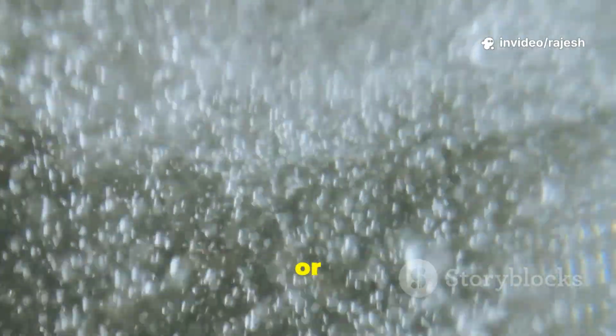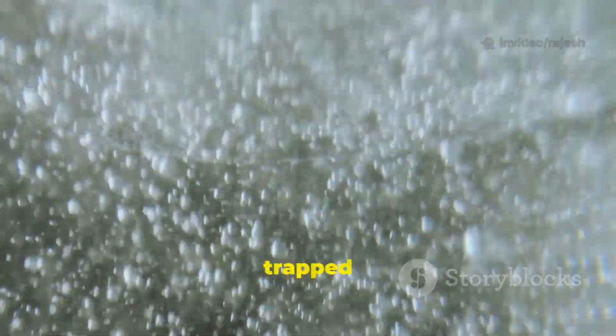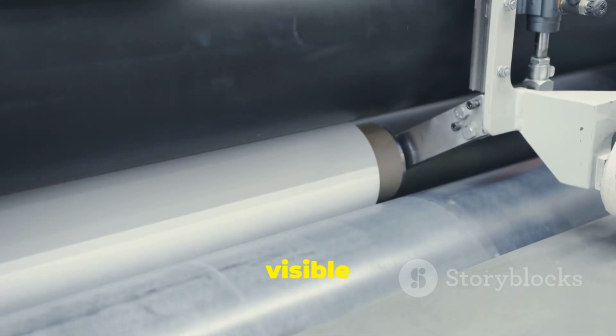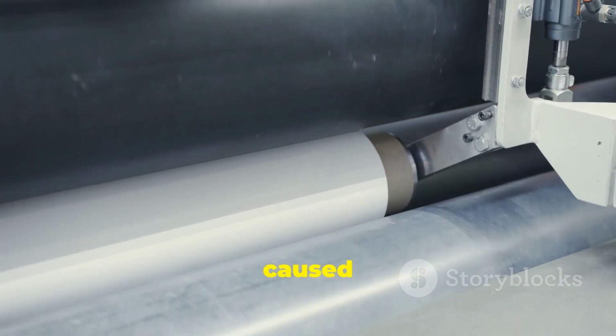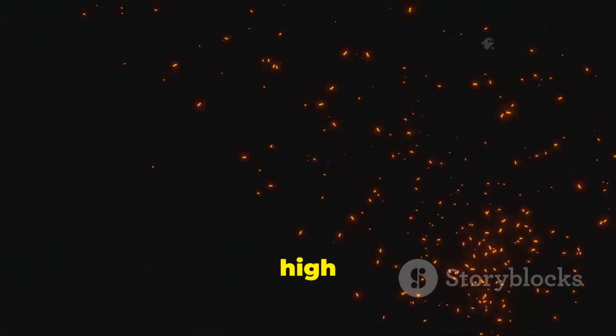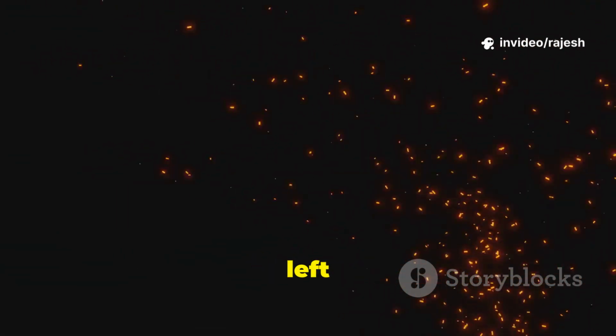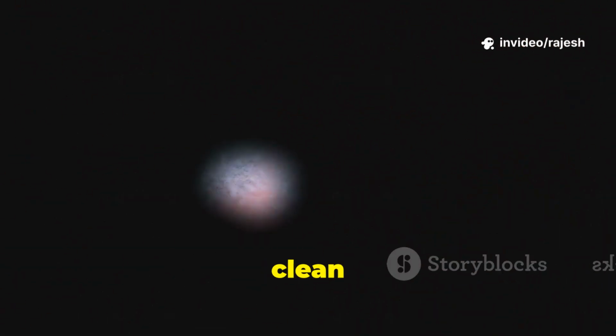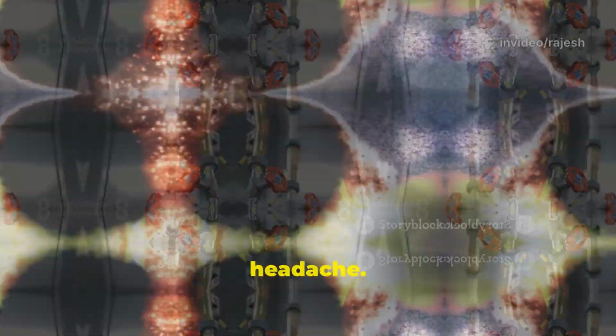Number 6, voids, or bubbles. You'll spot these as trapped air inside the plastic, often visible in cross-section. This is caused by air not escaping the mold, high injection speed, or even moisture left in the pellets. Keep your vents clean and your material dry to avoid this headache.